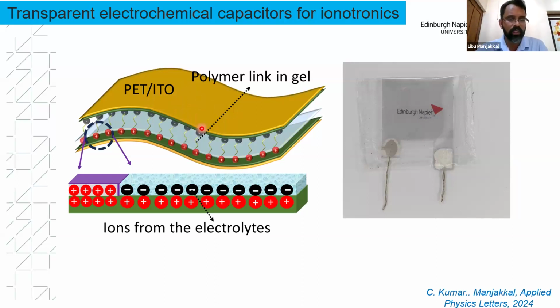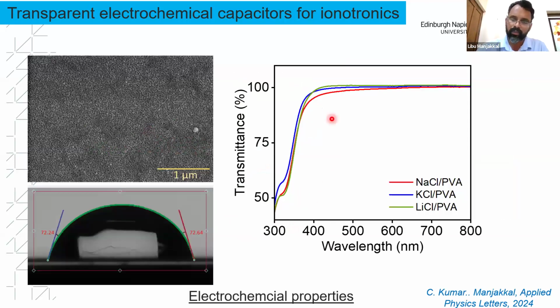This is the preliminary work in our group, where we developed an ionotronics-based technology, with the formation of an ionic gel for sensing applications. You can see here the transparent electrochemical capacitor we developed, and depending on the type of gel, we compared sodium chloride, potassium chloride, and lithium chloride-based gels. For this gel-based electrode, we initially made the transmittance study, and we found almost 99% transmittance. This is a surface image of the ITO electrode, where we got a contact angle of 72.6 degrees.